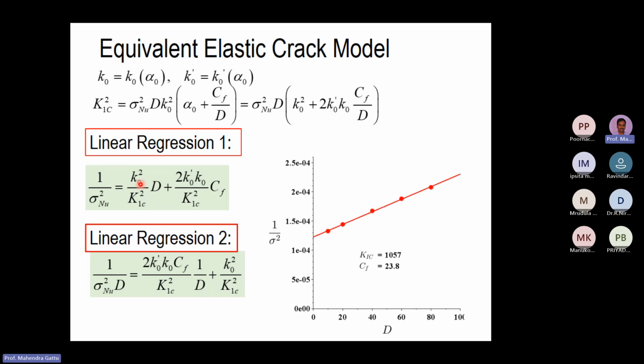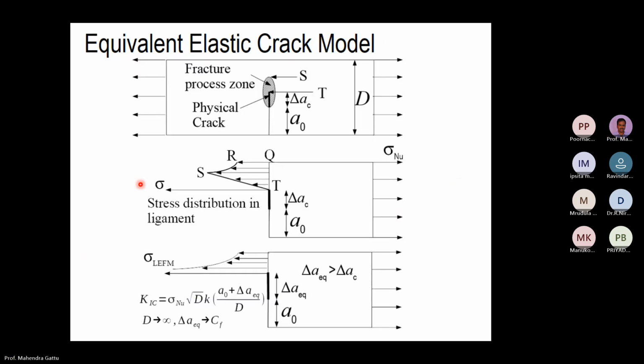I think you have missed the previous part, so I'll just go through that. What is happening here is at the crack tip, there is a fracture process happening. Fracture process means material is breaking up, and material breaking up means the material's load carrying capacity is getting reduced. So this ligament, this region, we can model using a cohesive crack model. That means that the peak stress has reached in this region and the material has started failing, so the load will drop down. That load dropping down is shown here. The maximum stress which the material can take is here, and beyond that, when you keep loading it, the material is softening. So this is the softening part.